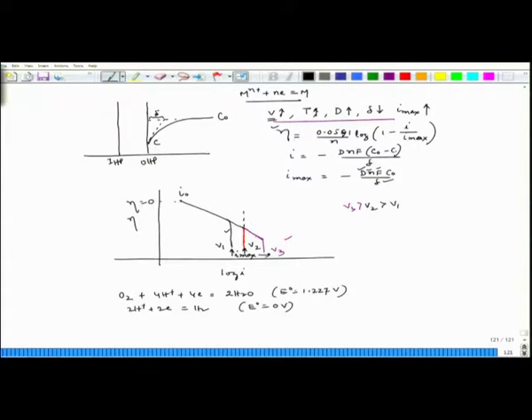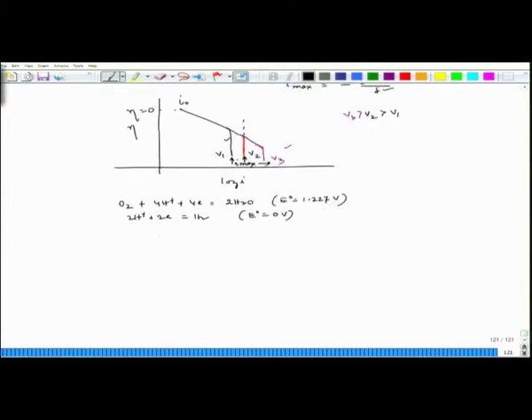If I try to see the response of cathodic polarization, as well as what happens in the concentration and activation polarization regimes, we can have a response like this. This is log I, this is overvoltage. Now, eta for the oxygen reaction is equal to 0 at this point, corresponding to the potential E0 equal to 1.227 volt. Remember, this is the equilibrium voltage, and at equilibrium voltage the overvoltage is 0 for that oxygen reduction. And if E is equal to 0 here, it corresponds to eta for H2 evolution being 0